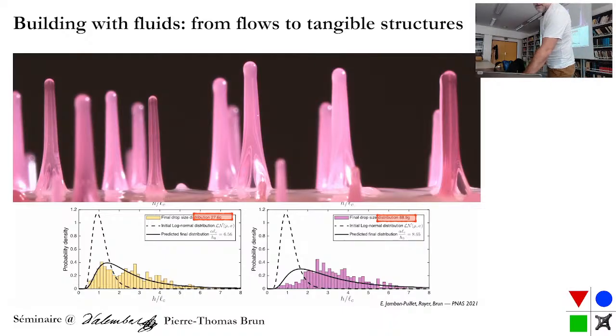Okay, so we were happy for a number of reasons, but in particular because we managed to make this high aspect ratio structure, which is suitable for some applications. However, what you want is high aspect ratio and high density. And here we're actually not accomplishing this because the density is inherited by the low acceleration case, so they're quite far. So we stretch them, but they're still quite far. So the question is, how can we make them tall and close?